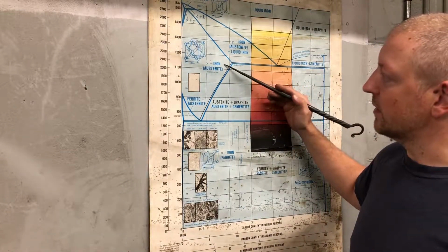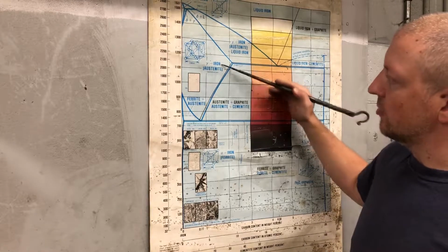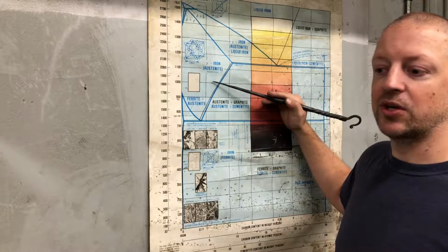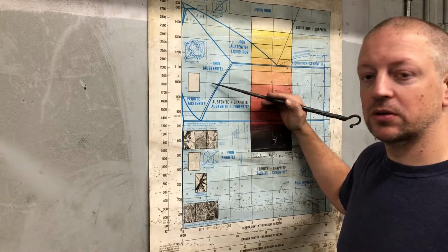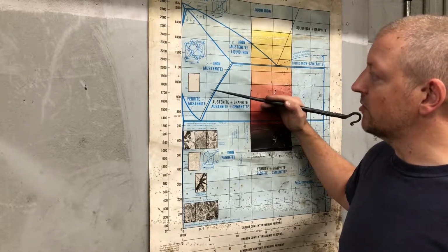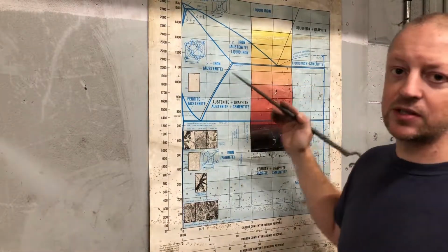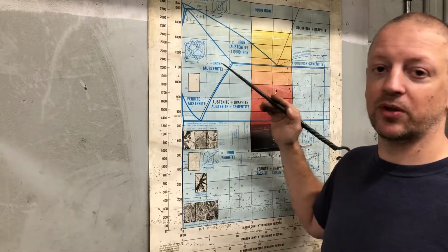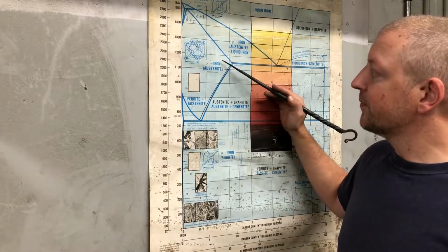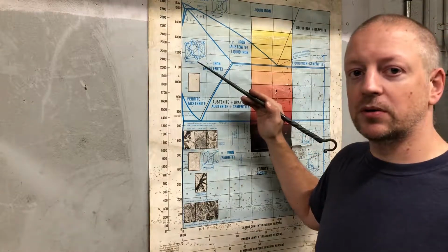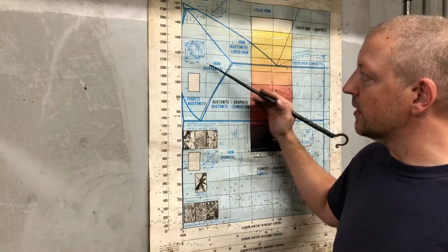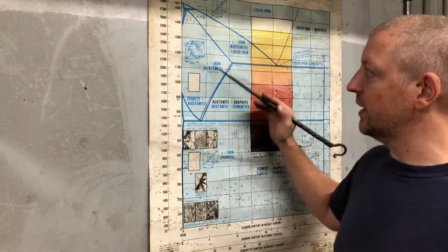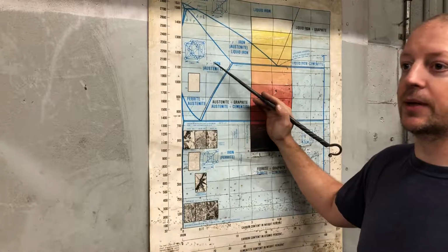So what will happen is that this pure austenite zone actually shrinks as you introduce those additional carbide-forming elements. This is why the cutlery-grade stainless steels, which have a lot of chromium, typically more than 12%, have a really small window to get full austenite. You're looking at a really tight area that you've got to hit.